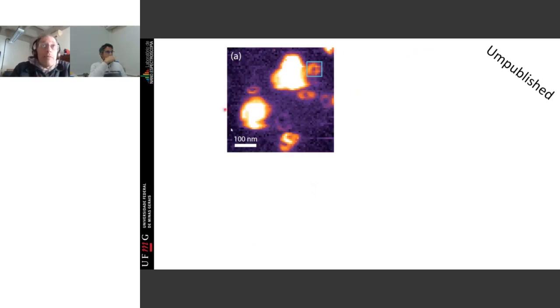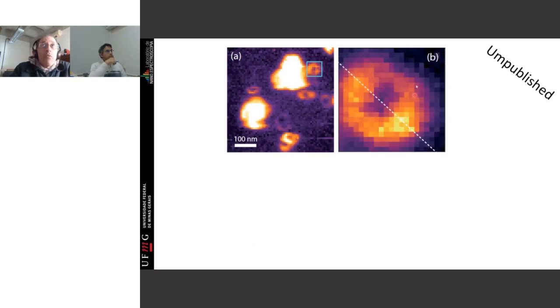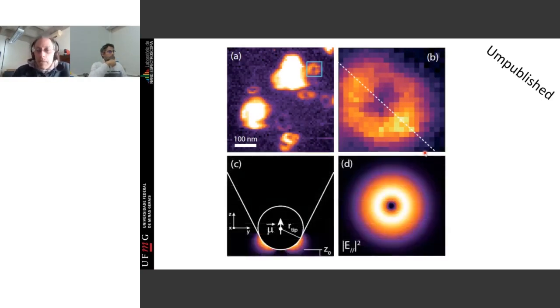This is, again, a Raman spectrum. This is a large graphene particle. This is a very small graphene particle. If I zoom on this, what you see is a donut light structure. So it's funny because you say, okay, this is a particle, or it's a donut. It's a particle being illuminated by a donut. What happens when you illuminate the material? This would be our nano antenna.